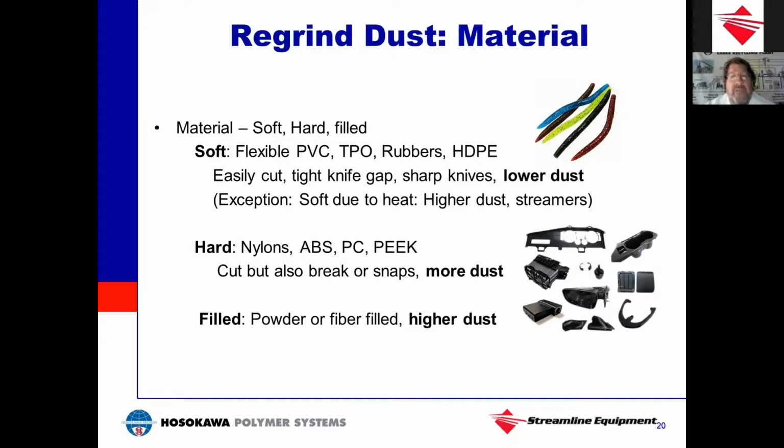There is one exception, which is if your material is really hot when it comes out. A trick that we like to tell customers is if you have a runner and you have a 2-minute cycle time, and a big thick runner that can be hot inside, you don't necessarily want to take that out and drop it right into a granulator. If you're using a robot, you can change it so that it comes out and holds to help cool it down a little bit, you could even put a fan in that area, and then drop it, and the robot goes back to its sequence, rather than the robot just waiting for the platens to open up and pull the next one. It could be cooling the part down.